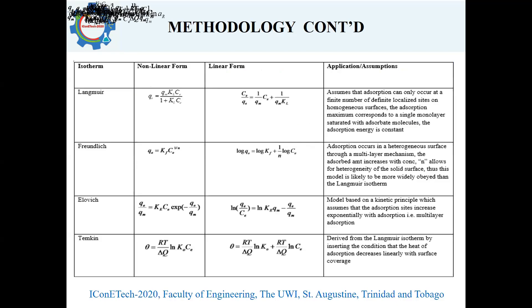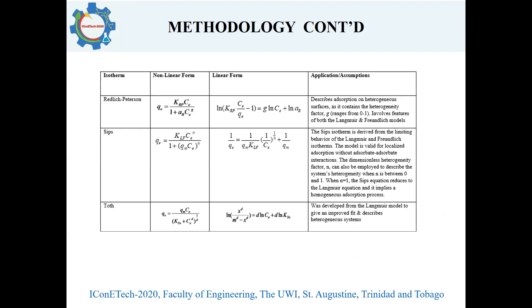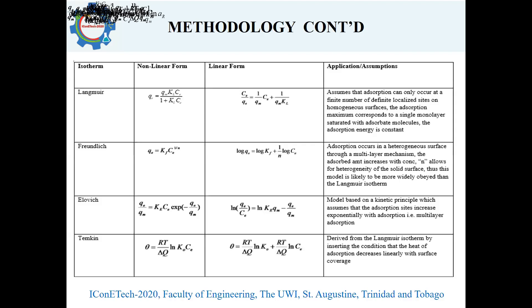This table presents some of the common two-parameter and three-parameter isotherm models used to describe the adsorption behavior of phenol onto activated carbon. For example, the Freundlich isotherm model, as well as the Redlich-Peterson and SIPS models, are similar in that they assume adsorption occurs on a heterogeneous surface through a multi-layer mechanism. There is a parameter N that accounts for the surface heterogeneity; when n takes a value between 0 and 1, the system is considered heterogeneous.